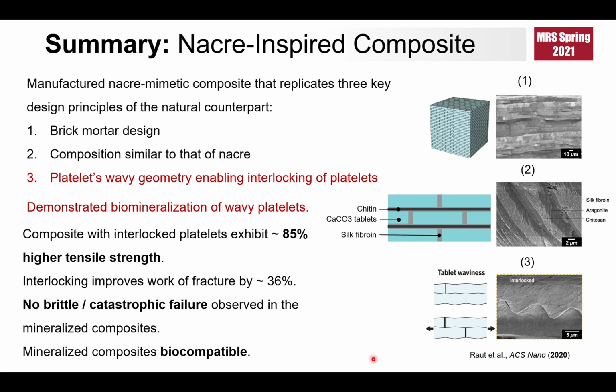So, in summary, we have manufactured a mineralized composite that encapsulates the 3 key design principles of the biological composite nacre. It incorporates the brick mortar design seen in nacre. It comprises chitosan, aragonite, and silk fibroin. Similar constituents are found in nacre as well. And it incorporates wavy platelets, resulting in interlocking of the layers, which is a strategy found in nacre to arrest platelet sliding.